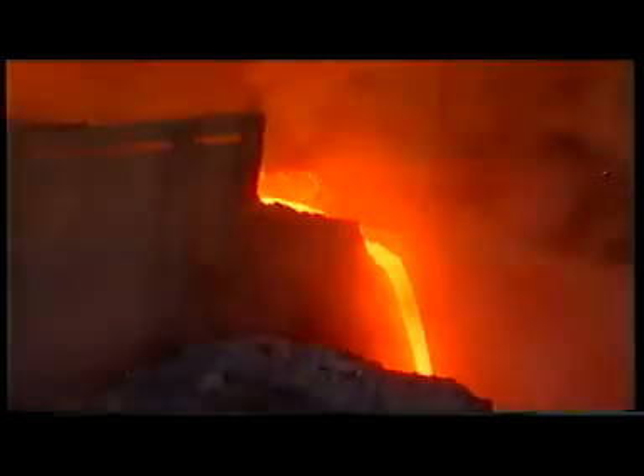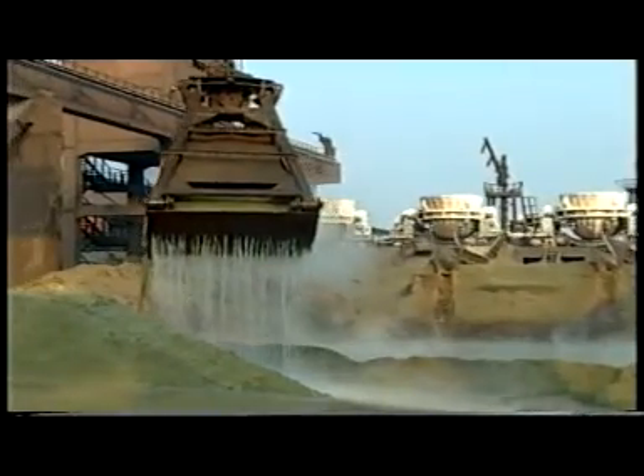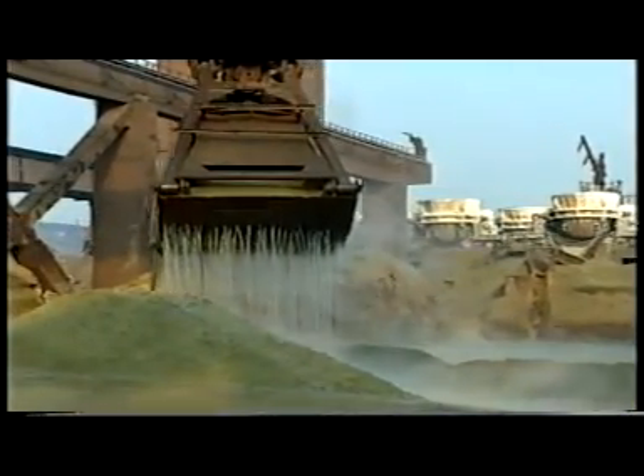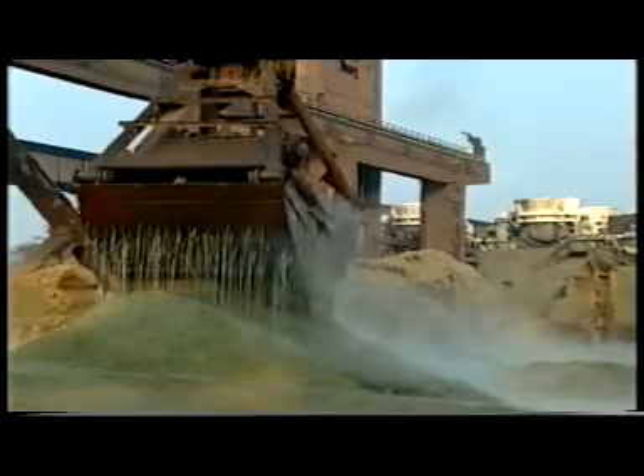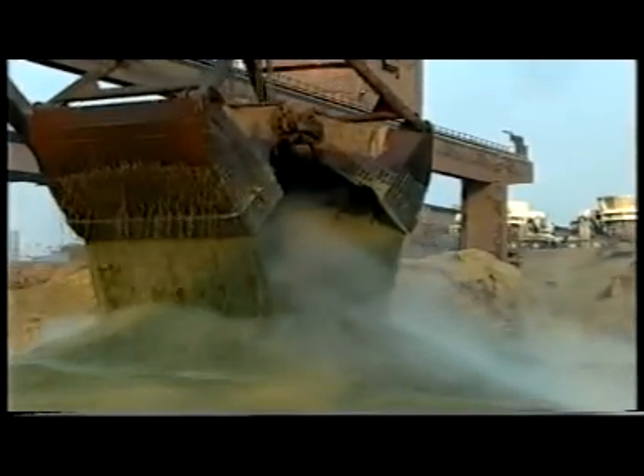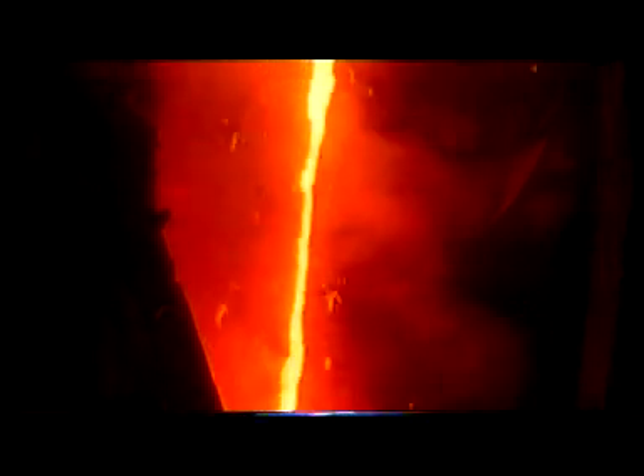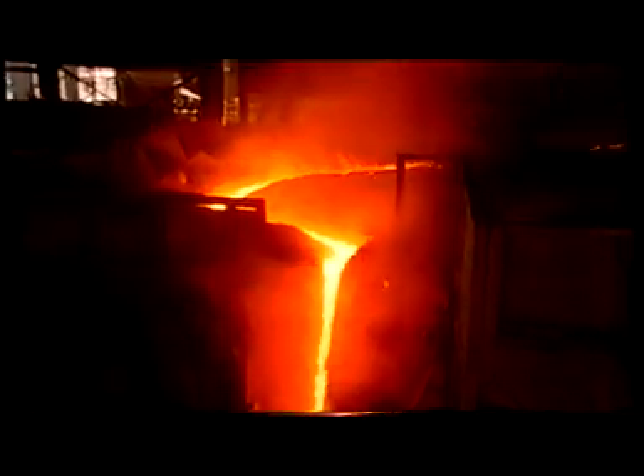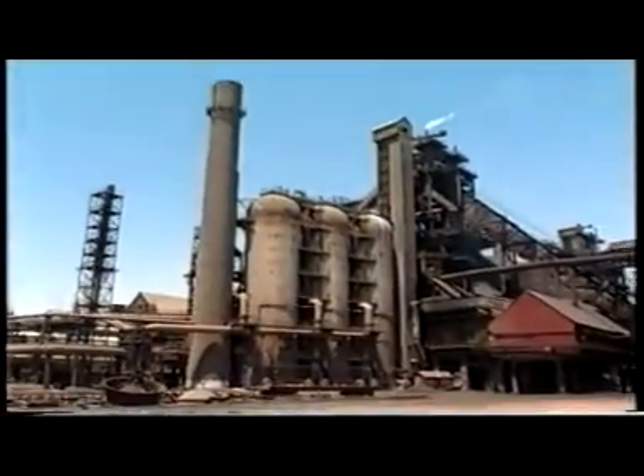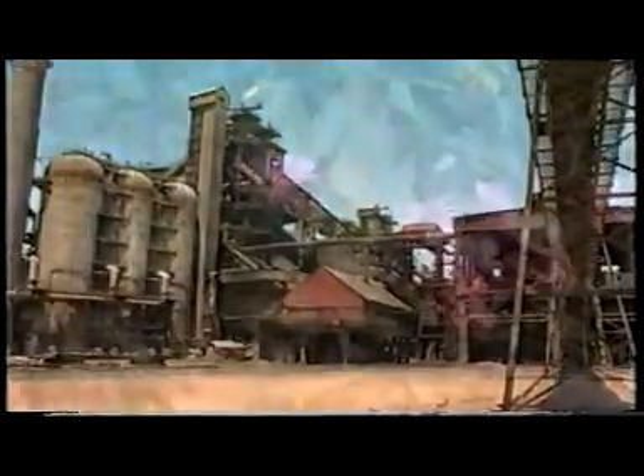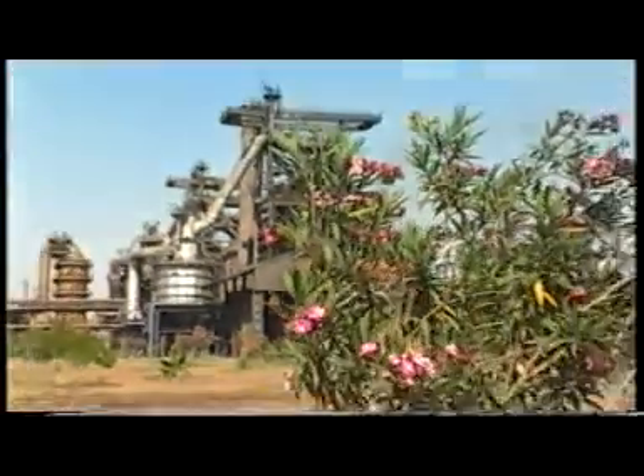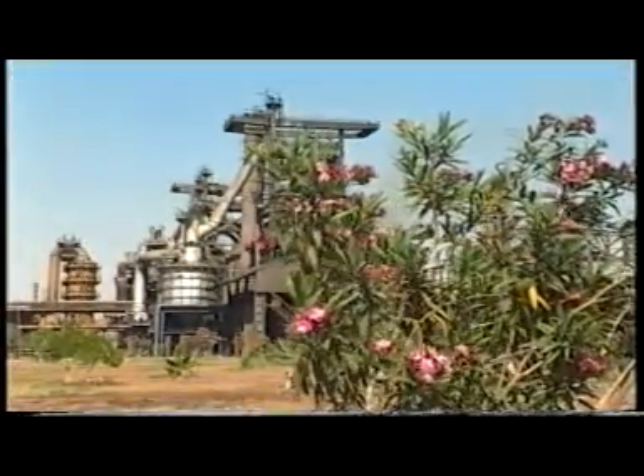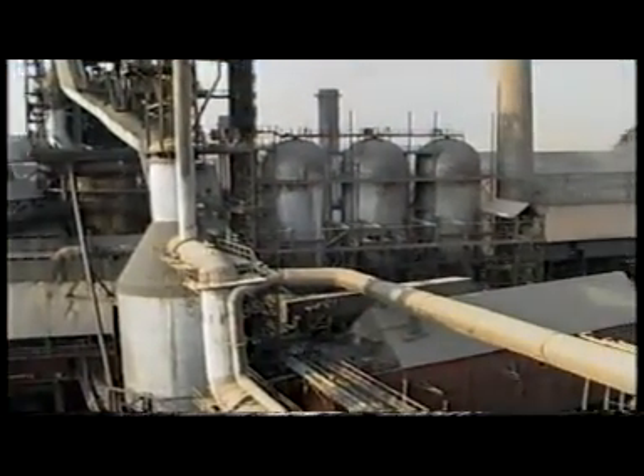The reaction between the charge and the reducing active gases inside the blast furnace lead to the reduction of the sinter where the reduced iron gathered as pig iron, while the other elements called slag, having amounts of about 600,000 tons per year, usually sold to cement manufacturing companies, while the production of pig iron amounts to 1.5 million tons per year, coming from 4 blast furnaces which are unique and the only ones in Egypt. They are able to extract hot liquid iron from sinter.